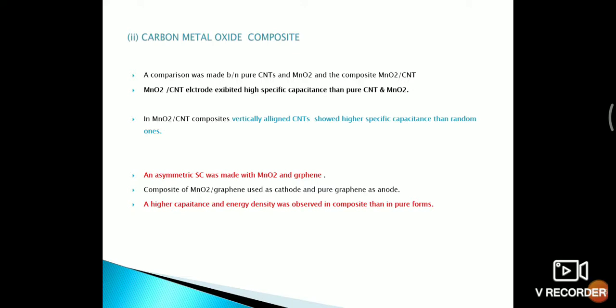Next is carbon metal oxide composite. A comparison was made between pure CNTs and MnO2 and the composite of MnO2 CNT. MnO2 CNT composite electrode exhibited higher specific capacitance than pure CNT and MnO2. In MnO2 CNT composite, the vertically aligned CNTs show higher specific capacitance than the random ones. An asymmetric supercapacitor was made with MnO2 and graphene. This composite of MnO2 graphene was used as cathode and pure graphene was used as anode, and a higher specific capacitance and energy density was observed in this composite than in its pure forms.